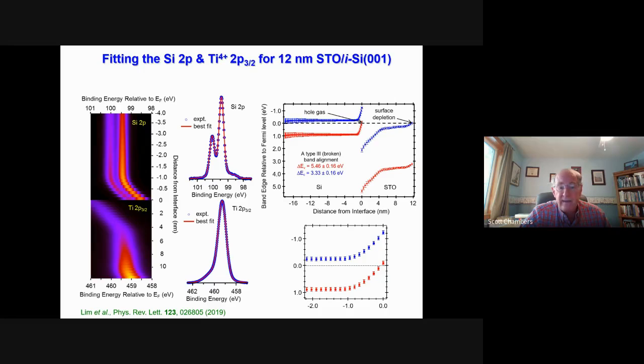If we take a look at the magnitude of the built-in potential from the photoemission, blow up that region right at the top of the silicon layer, we get 0.98 from the photoemission, and we get 0.9 from the Hall, which is pretty darn good agreement.